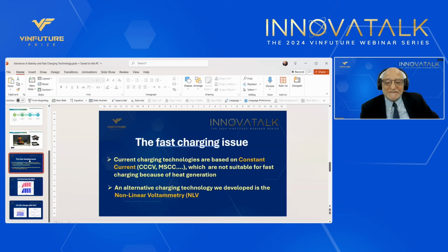So for fast charging, batteries now are charged using mostly constant current based technologies or methods. And constant current is like CCCV, constant current, constant voltage, or MSCC, which is the multi-stage constant current. These technologies are not able to fast charge batteries because of heat generation. Forget about charging a battery from 0 to 100% in 10 minutes using a constant current. The battery will heat up and there is a risk of thermal runaway.